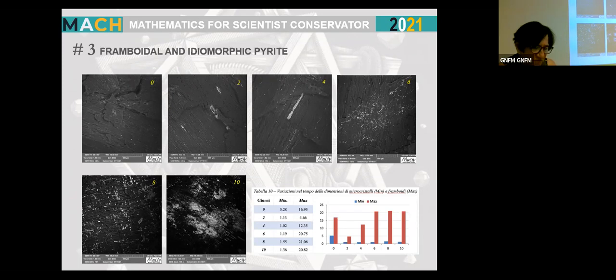The calculation of the minimum dimension of the crystal and of the framboidal structure shows that the values are in line with the literature data. The dimension of the pyrite framboids varies from 4.6 microns on the 2nd day of immersion to 21 on the 8th day, to remain stable on the 10th day. Microcrystals, on the other hand, are somewhat uniform, varying between 1.2 and 1.5 micrometers. The exception is the untreated sample with a limited number of crystalline elements, but larger in size. This suggests that the increase in the number and size of framboids in samples treated with the chelator is related to the neoformation of pyrite microcrystals induced by the presence of the EDTA.